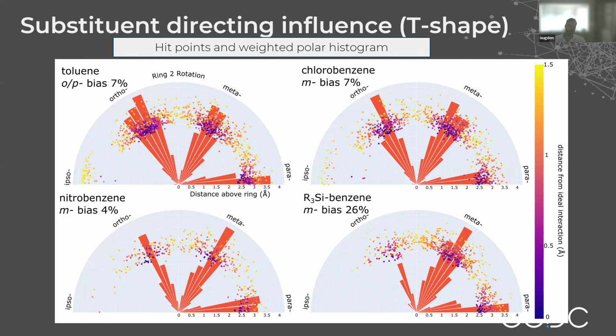For chlorobenzene, so this is an electron withdrawing group, it should be meta-directing, and you can see a slight bias of 7% there. The same with nitrobenzene, which is a much stronger electron withdrawing group, but only a 4% bias. When you get very large substituents like R3Si, you see a much more significant bias towards the meta position. And so that's suggesting to us that steric interactions are quite an important consideration there.